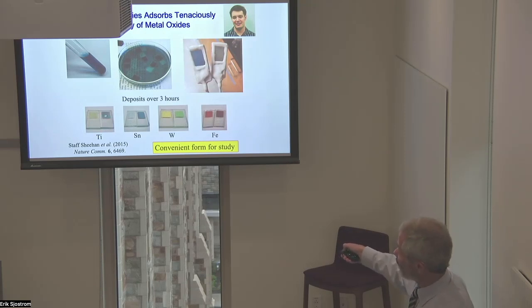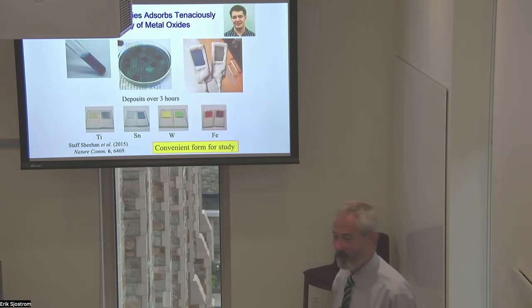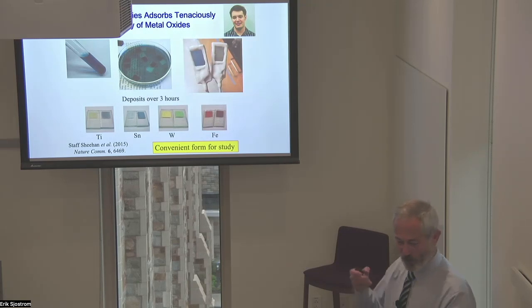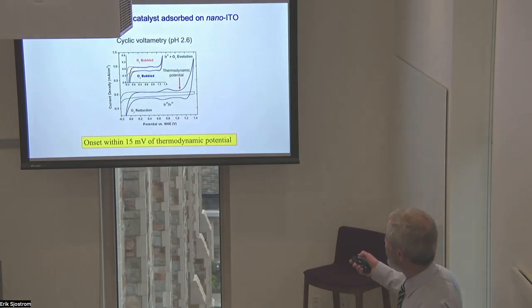So there's TiO2. It's incredibly tightly bound. In the case of TiO2, we found that we can't strip it off except using conditions that dissolve TiO2. So it's basically grafted onto the surface as part of the oxide lattice. And so it's really tightly bound. And it's an incredibly good catalyst even when it's bound on the surface.